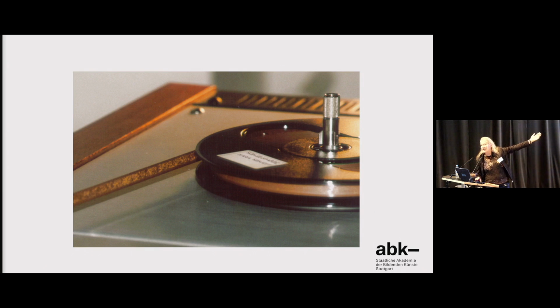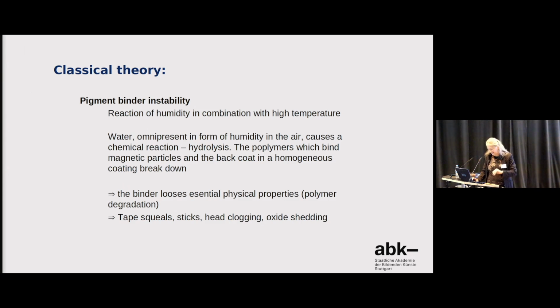So this should never ever be the case. You should never ever spool a tape so far. If you have a tape which looks, or which you know from the tape brand that it might be sticky, then you should never risk losing magnetic layers. So I always have a special light situation where I can control at a low winding speed if some particles come off or not. This is the classical theory.